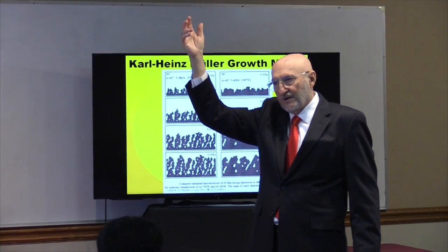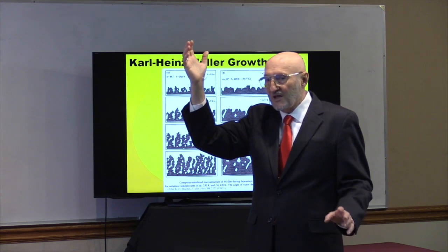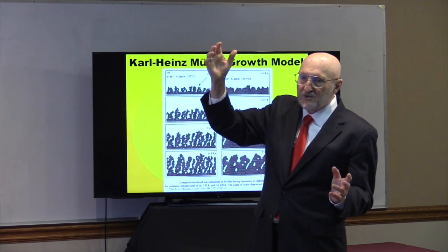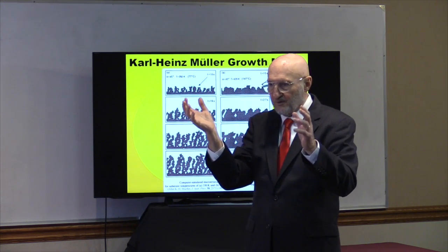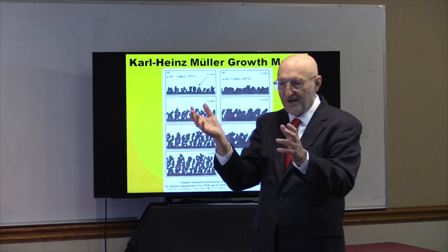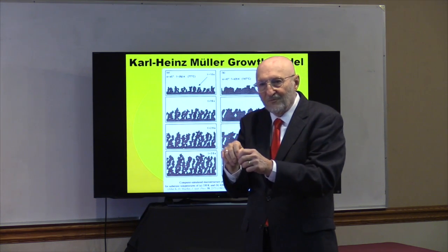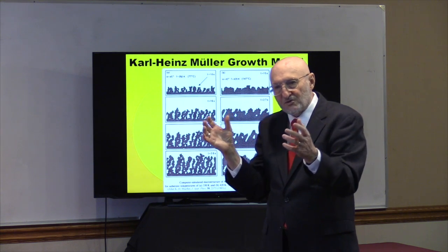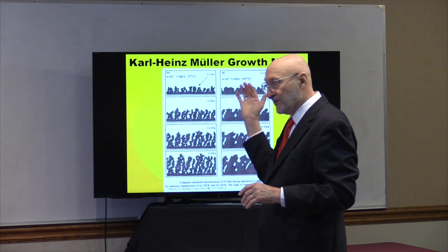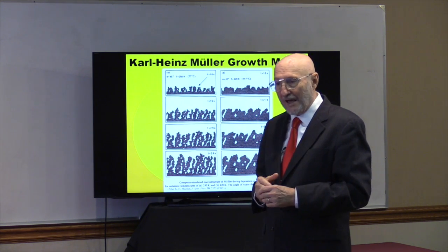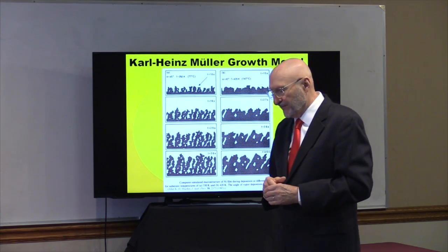On the other hand, if the substrate was warm, and it gets up there, it at least has the energy it came with. So it can kind of move around a little bit. And if there's another magnesium fluoride next to it, it can kind of nestle in closer and snuggle up. And then it loses its energy and it's stuck there. So the temperature of the substrate is important, which is what I showed you in the previous slide. And that's what this is illustrating.